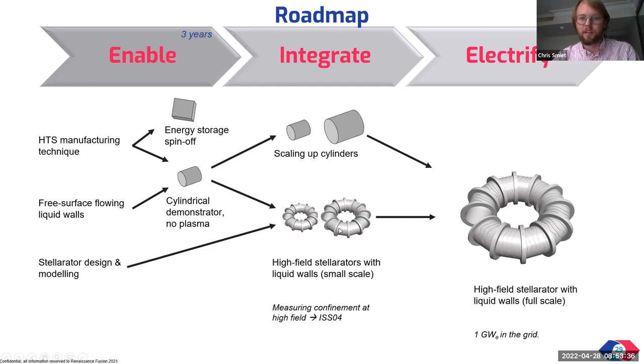At the same time, in this phase, we're scaling up. So we're making larger and larger cylinders so that when we get to the point where we want to deploy or electrify, we are making these large HTS coated cylinders that can be shipped directly to either an end of life fission or carbon plant and can replace the dirty or the end of life core with a stellarator heat source that can generate electricity. And so we can directly start delivering energy to the grid and start transitioning away from carbon sources.